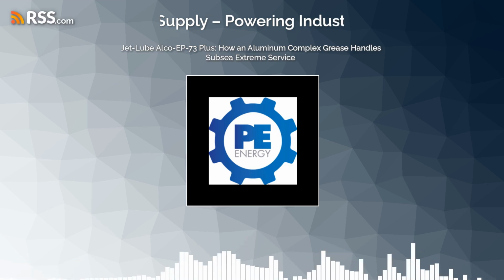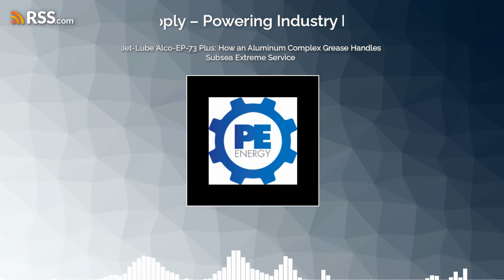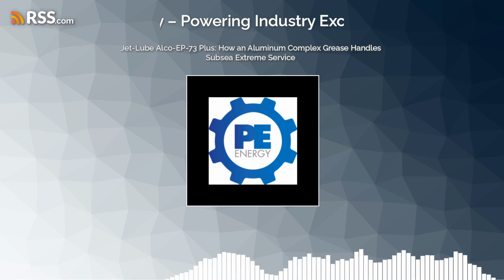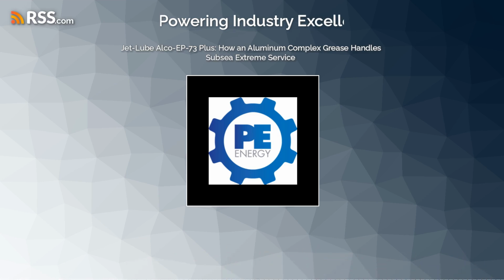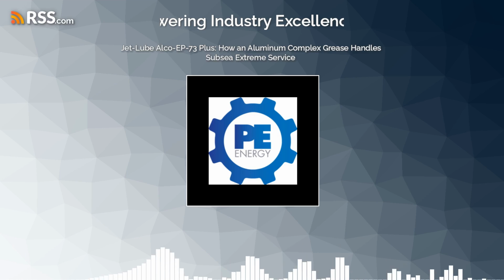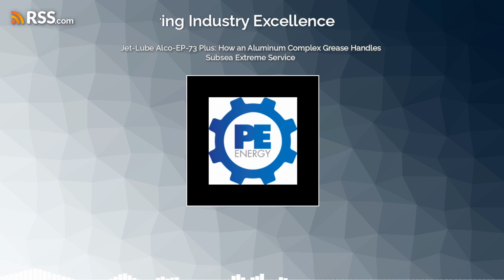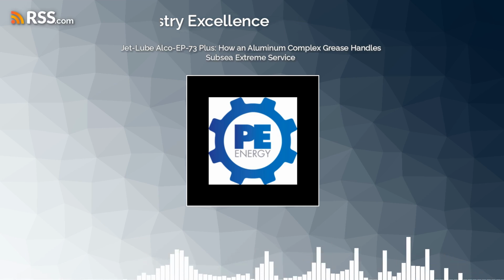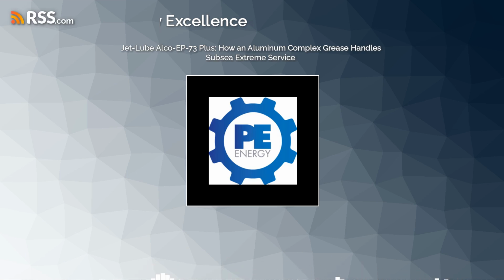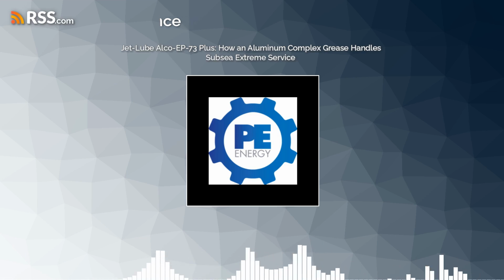Well, wait, the maximum operating temp is listed at 450 degrees Fahrenheit, but right below that, the flash point, where it can temporarily ignite, is only listed as greater than 430 degrees Fahrenheit. Right, the flash point. Isn't that an incredibly tight margin for error if things get too hot? Like, if your operating temp is 450, but your flash point is 430, aren't you routinely operating a machine inside a window where its lubricant could literally catch fire?